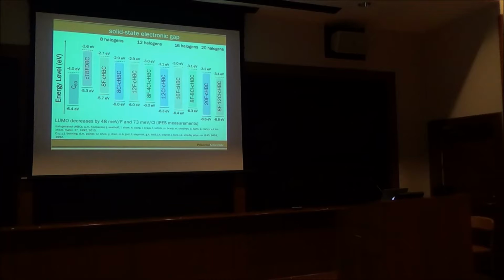The LUMO energy level drops by about 50 millielectron volts per fluorine and by about 70 millielectron volts per chlorine. This is nice because it generates a design rule for us, so we can predictively mix the next generation of compounds by knowing how much it affects the optoelectronics of the compound. Now with this, we can make devices.